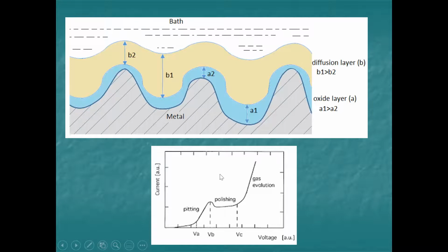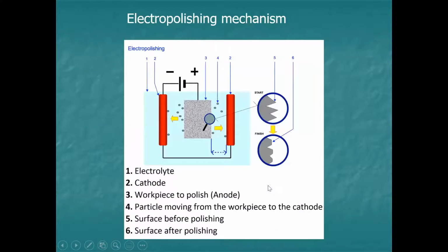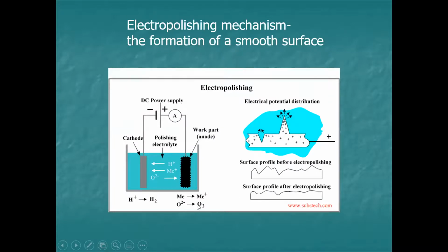But in the case of this particular type of electrolyte, instead of just making a passive film, what we're actually doing is we're polishing it, electropolishing it to be exact. And we want to operate the potential in this flat region here. If we do that, we will get a nice surface finish. If we only hold it down here, not high enough potential, we're just going to get pits in the material and nothing's going to work properly. And if you go too high in potential, we're going to start getting too much gas evolution. And that gas evolution will take place here. We want to try to avoid this reaction if we can. We're getting oxygen because that will interfere with the smoothness of the operation.